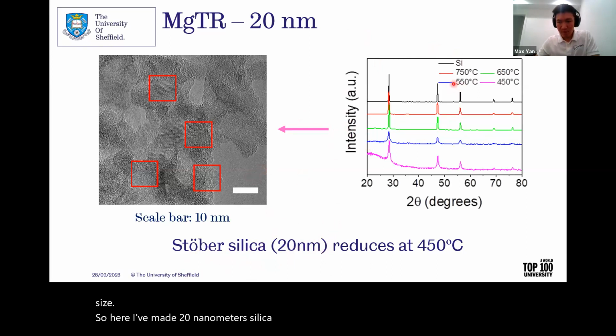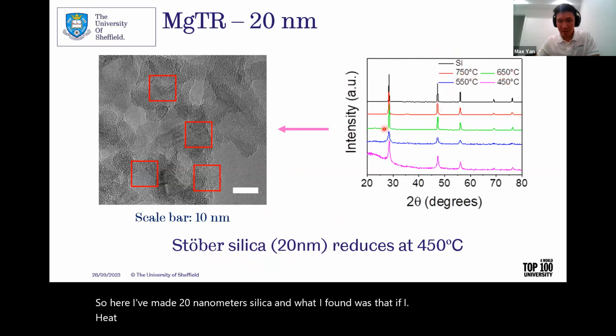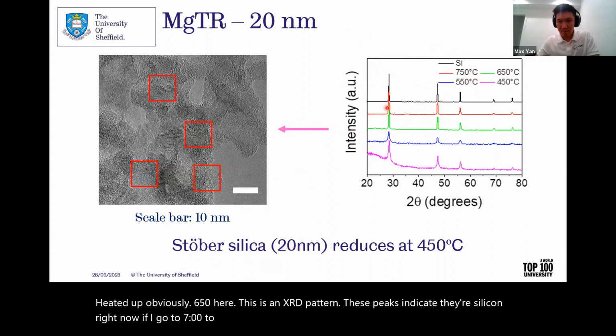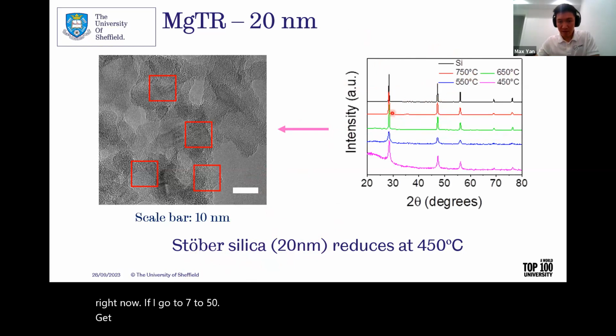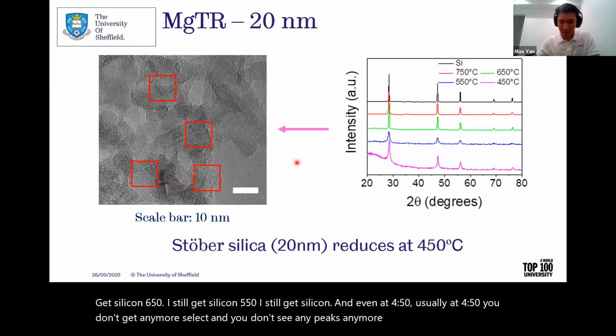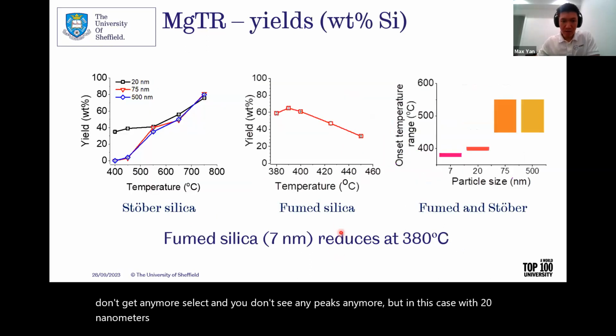And what I found was that if I heat it up, obviously 650 here, this is an XRD pattern. These peaks indicate there's silicon, right? Now, if I go to 750, I get silicon. 650, I still get silicon. 550, I still get silicon. And even at 450, usually at 450, you don't get any more silicon. You don't see any peaks anymore. But in this case, with 20 nanometer silica, you do.